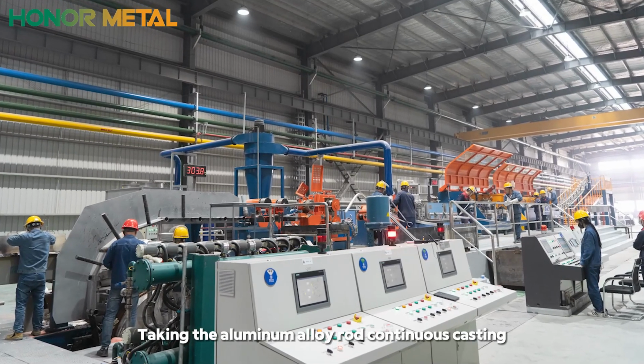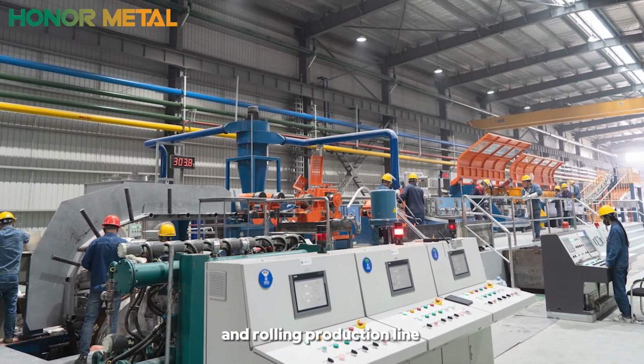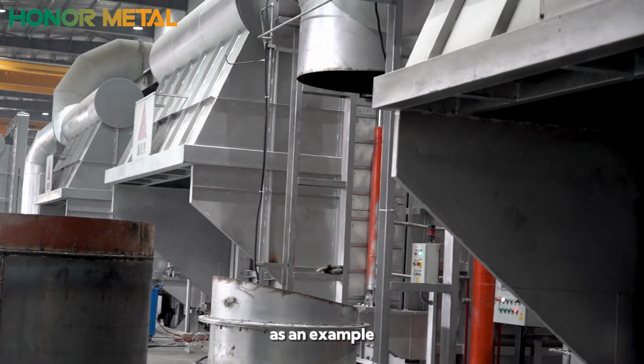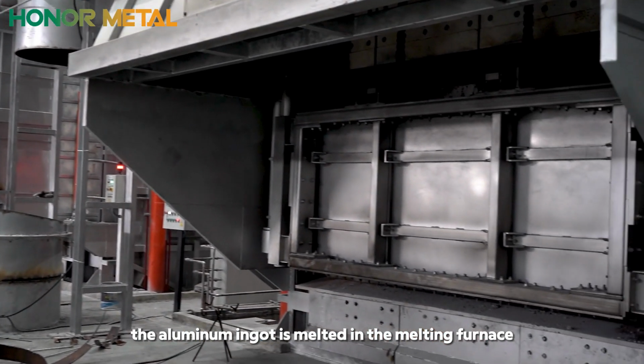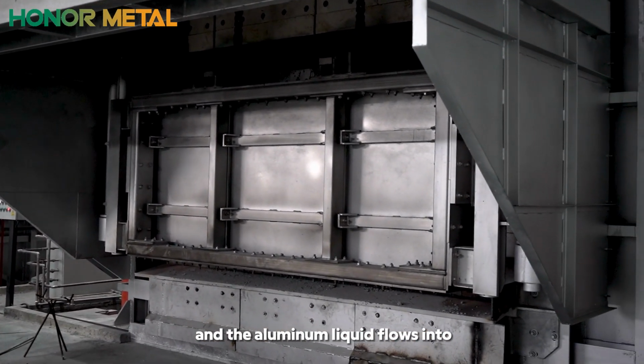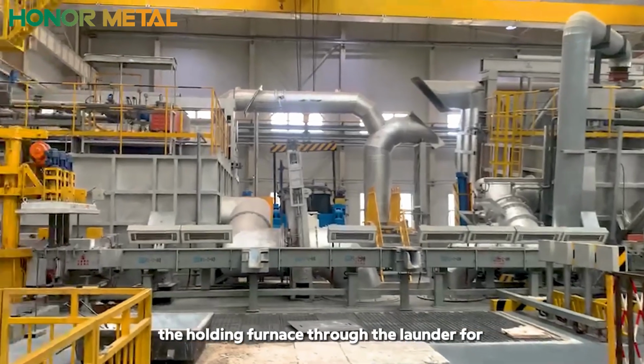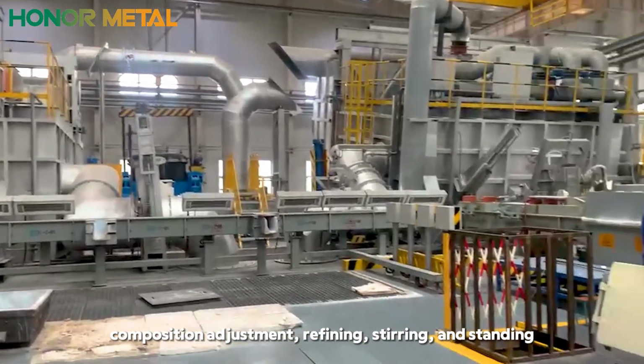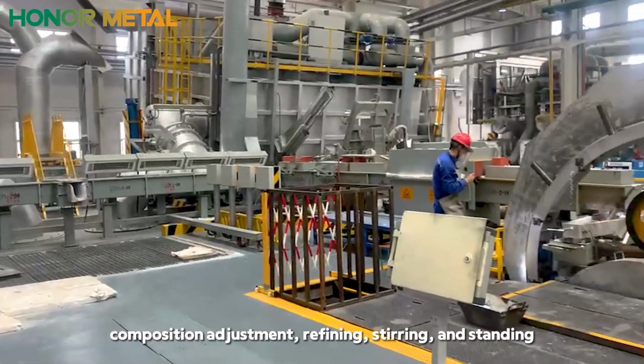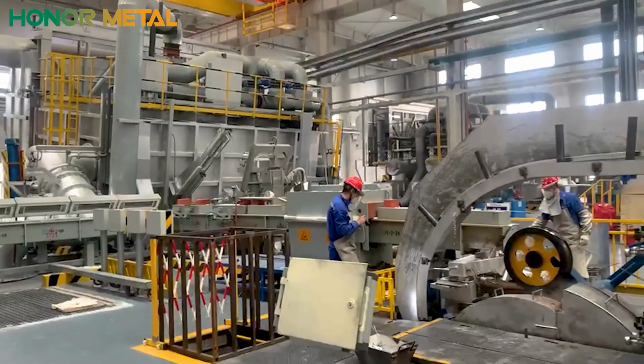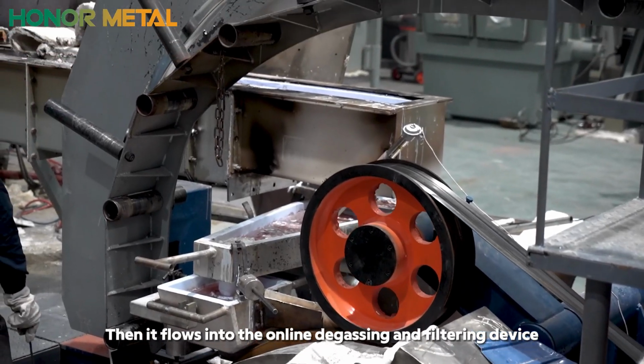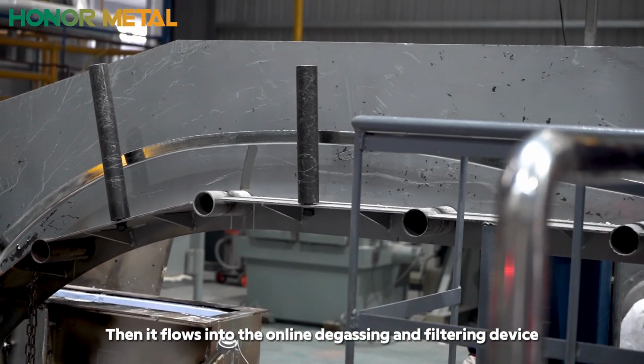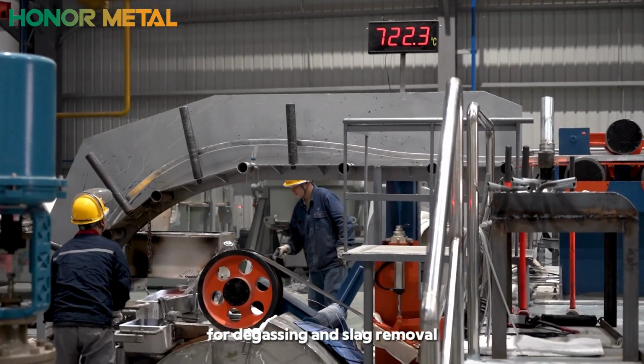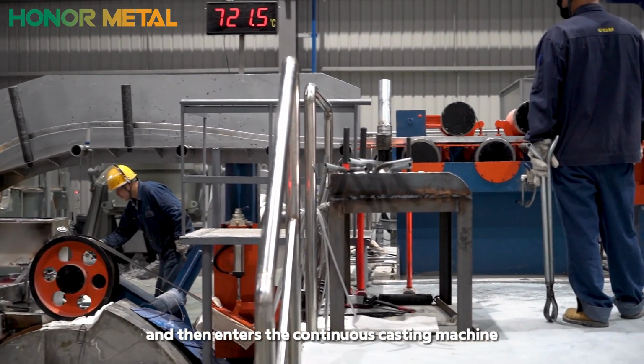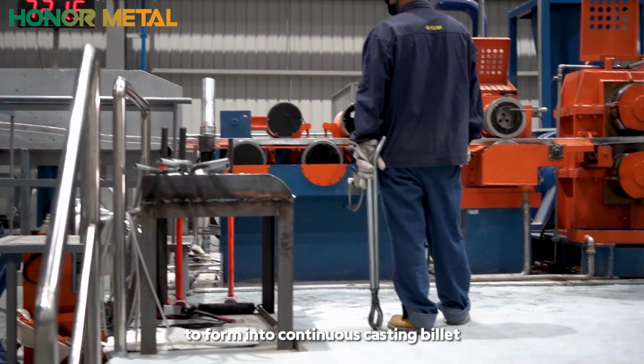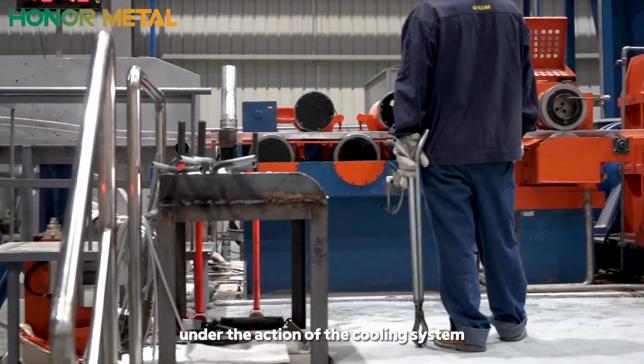Taking the aluminum alloy rod continuous casting and rolling production line as an example, the aluminum ingot is melted in the melting furnace, and the aluminum liquid flows into the holding furnace through the launder for composition adjustment, refining, stirring, and standing. Then it flows into the online degassing and filtering device for degassing and slag removal, and then enters the continuous casting machine to form into continuous casting billet under the action of the cooling system.